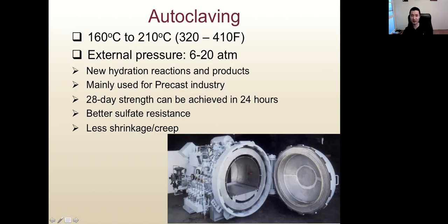Because the pressure is very high, the water in the concrete will not boil, at 6 to 20 times atmospheric pressure. So we have a totally new hydration reaction and new hydration products, very different from the chemical reaction at room temperature we discussed in earlier lectures. It is only used in the precast industry because we cannot bring this autoclaving oven to the field.